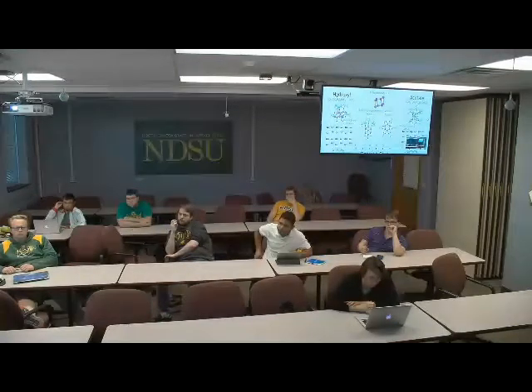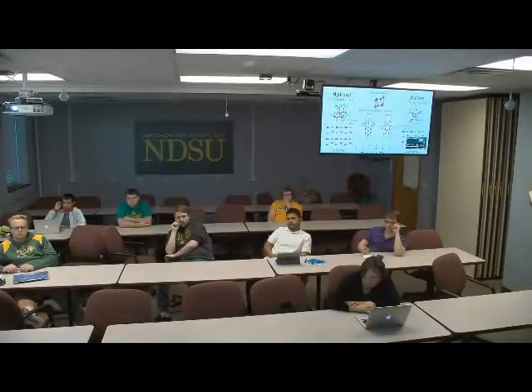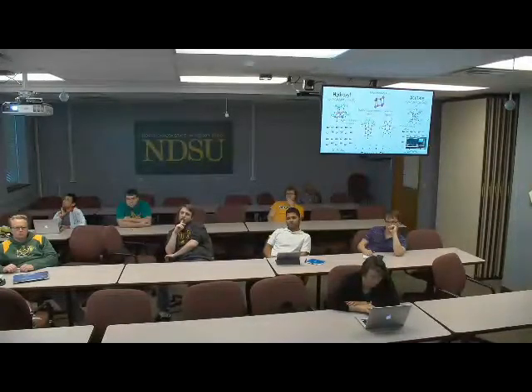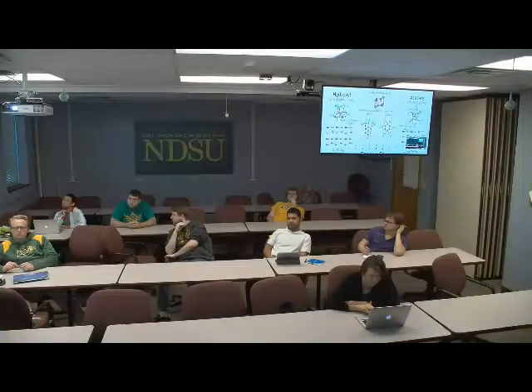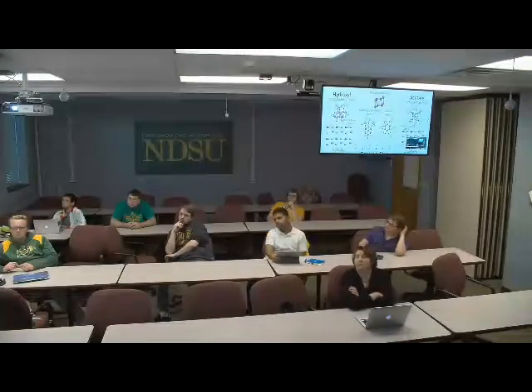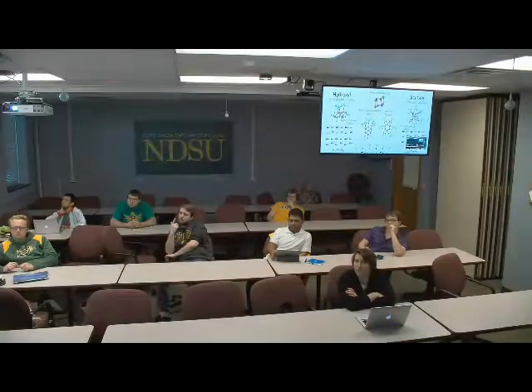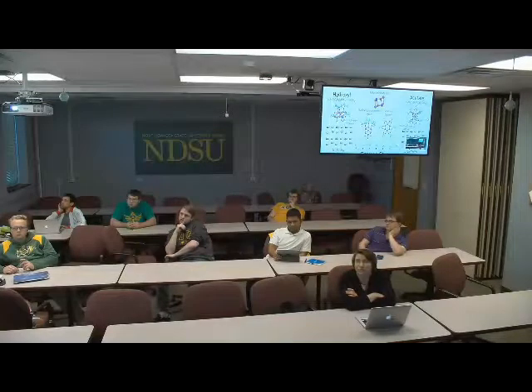So this is interesting effect, but it's a lot of work, and it's not clear that it is necessary right here. But if you do 2 quantum dots or quantum dot with periodic structure, this effect is gone. So it is just much more comfortable to, as you know, work with dots rather than periodic structures with mismatching lattice periods. Same is in the work by DM. In your recent publication, you have infinite periodic nanotube and finite size quantum dot. So your periodic size is not suffering of lattice mismatch. If you try to put nanotube on the infinitely periodic slab of silicon, it will be big strain and it will be major complication.